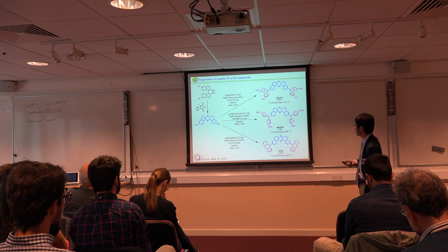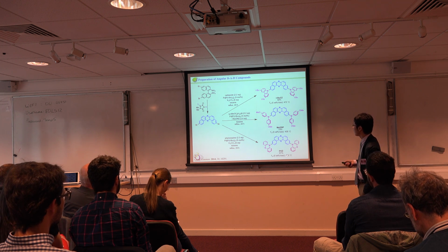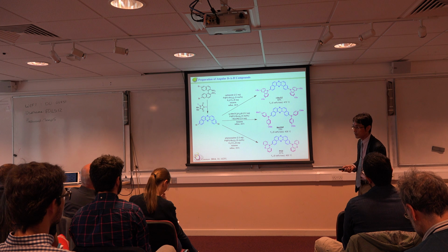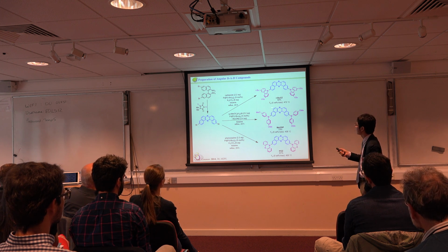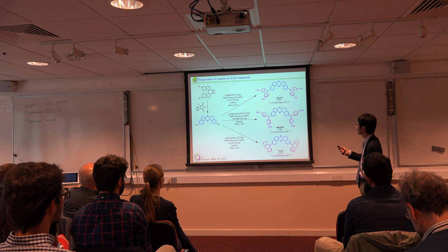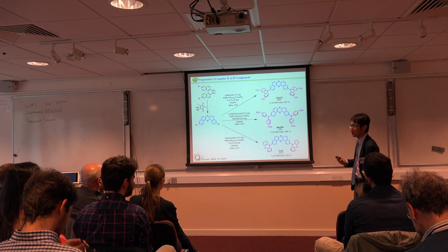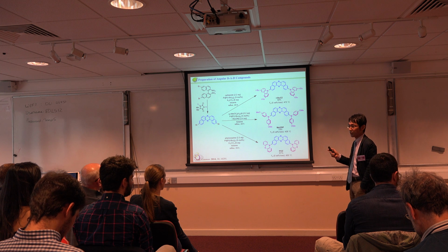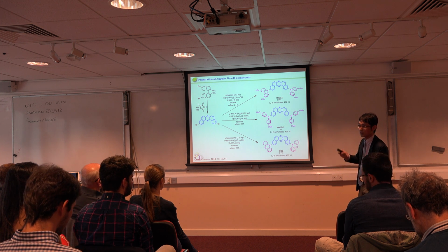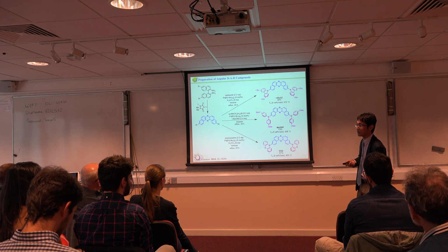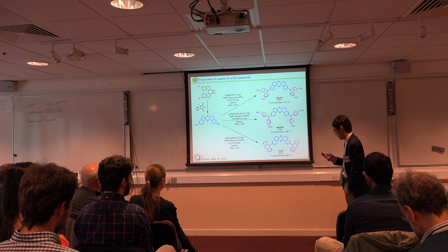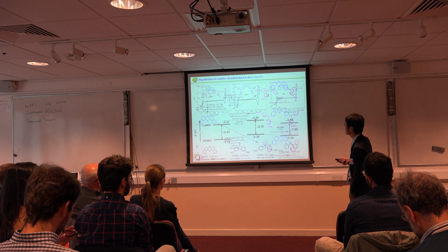These compounds also showed very high thermal stability. For example, the decomposition temperature is over 400 degrees Celsius. That can tolerate evaporation during the fabrication of materials or devices.